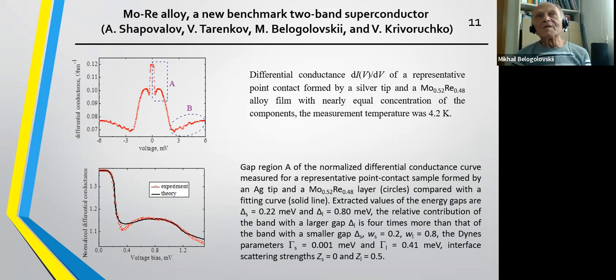But if such an interaction exists, not strong, of course, otherwise there will be a single gap, but some moderate one, in this case we could observe some new issues which are not present in single-band superconductors. So it is important to find new two-band superconductors and to perform experiments. So we proposed molybdenum-rhenium alloy as such a new two-band superconductor. We performed tunneling and point contact spectroscopy measurements, and the results are shown here.